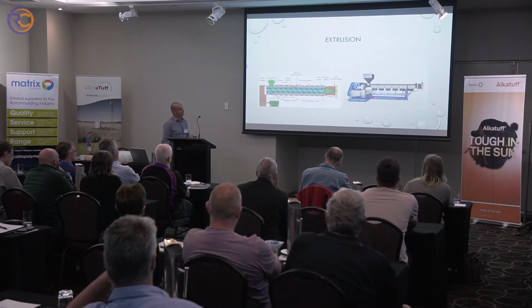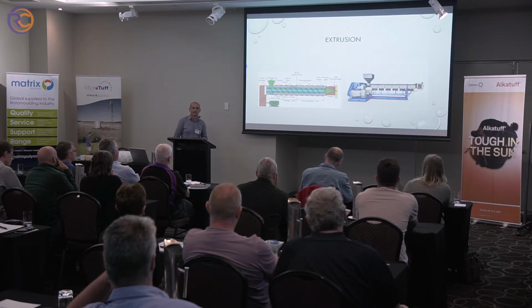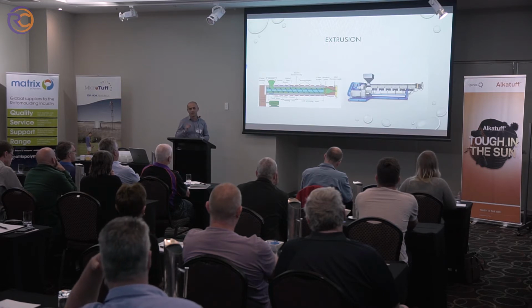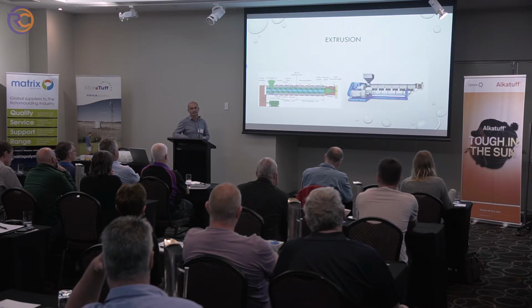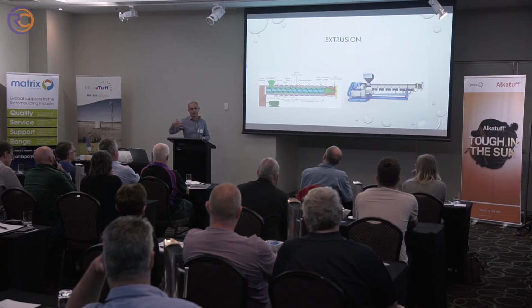And the most important part of the extrusion process is the melt temperature. The melt temperature is measuring the actual temperature of the resin. What we don't want to do is process that material too hot, because it starts taking out all the additives, for instance the antioxidants, that are used in your process to protect the product during the processing. So it's very important to make sure you don't go too high in the melt temperature.